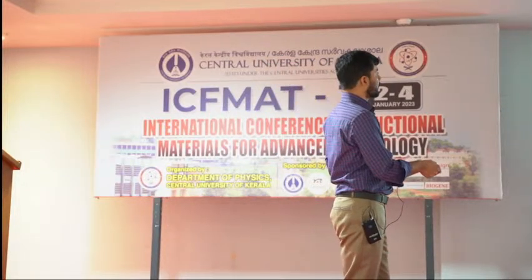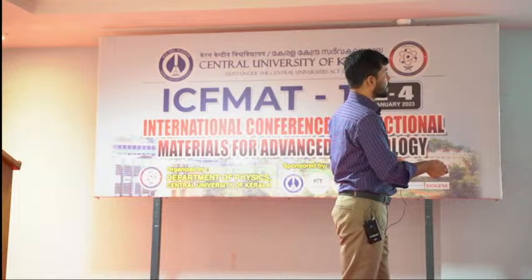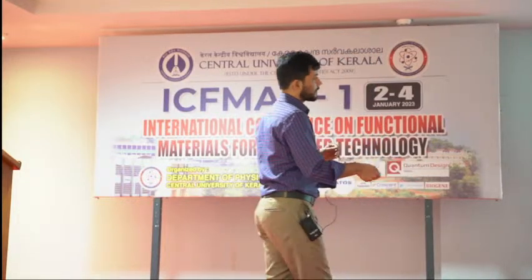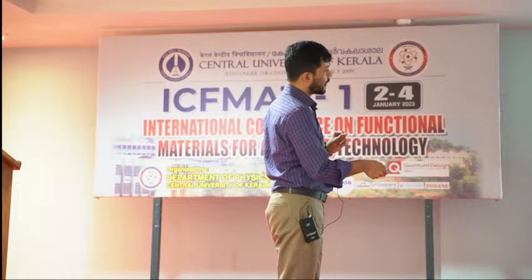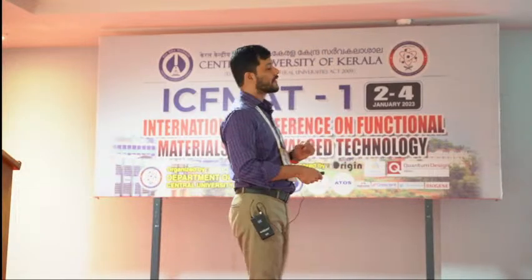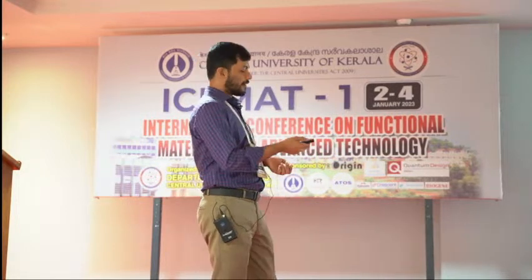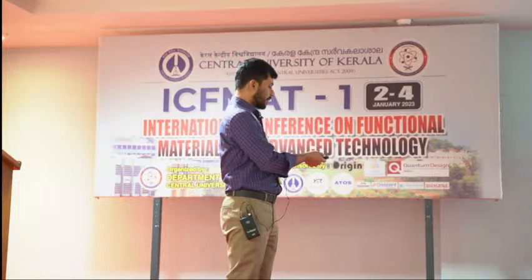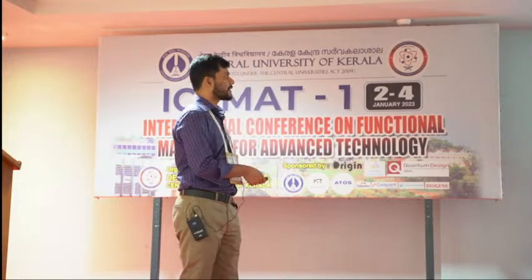The line width is much higher, about 50 nanometers, below the threshold. Once you reach the threshold, the line width falls to very low values like 5 nanometers. That is the kind of line width you will have from such a random laser. These are the properties that we got for our random laser.